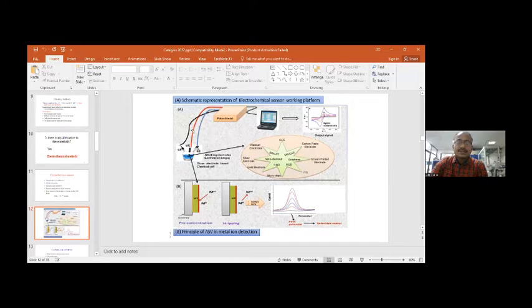So here in this electrochemical cell, we can see the counter electrode, working electrode, and reference electrode. The working electrode can be a glassy carbon electrode, carbon paste electrode, indium tin oxide electrode or screen printed electrode, and we can modify it using various substrates like single walled carbon nanotube, multi-walled carbon nanotube, graphene, quantum dot, nano diamond. So these are the various modifying materials. We can easily paste or drop cast them upon the glassy carbon electrode, which then acts as the working electrode. The reference electrode is Ag/AgCl, a common reference electrode, and the counter electrode is probably a platinum electrode.